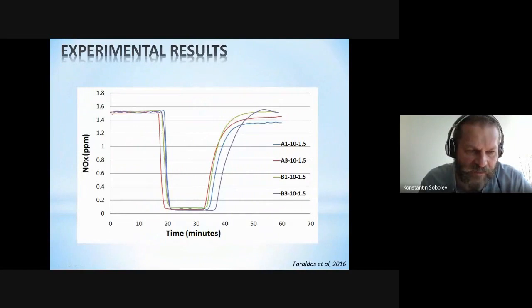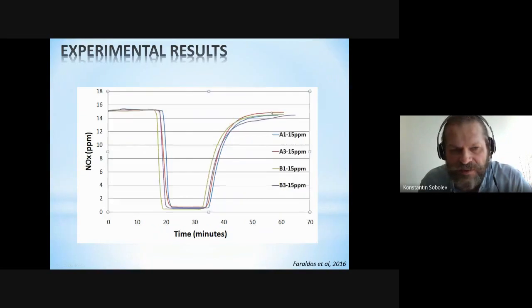You can see that some of the coatings are very effective at relatively low concentrations. 1.5 ppm is a NOx concentration of interest, and you can have better than 95% conversion of NOx gas in the chamber. You can see the initial concentration. Here the UV light started, and the concentration rapidly drops as it is converted. Here we switch off the light, the chamber is filled with NOx gas, and the concentration is restored.